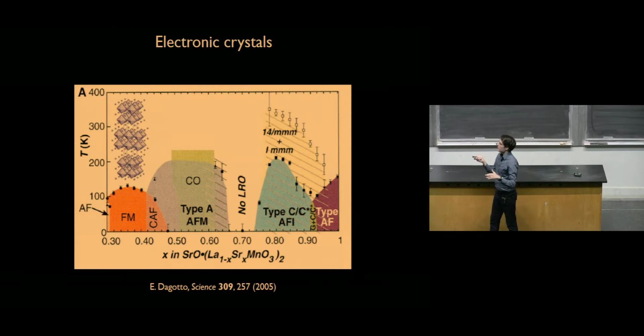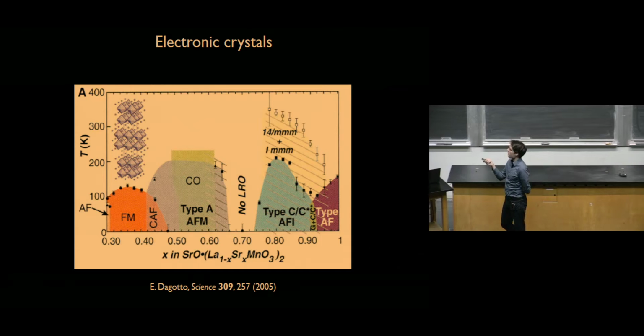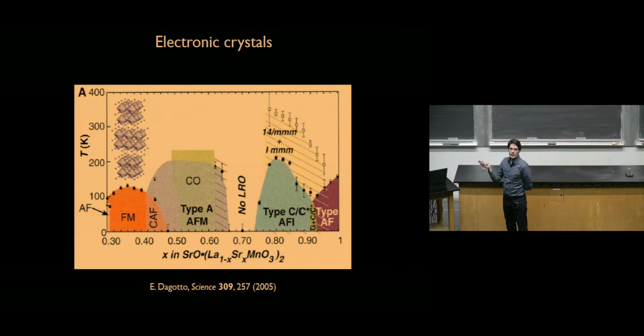And then as you change the doping, for instance, you suppress one, and another one starts to appear. And at this point, this ferromagnetic phase is suppressed, and the canted antiferromagnetic phase starts to appear here. And then in this region, you have charge order. So you have a lot of underlying instabilities.